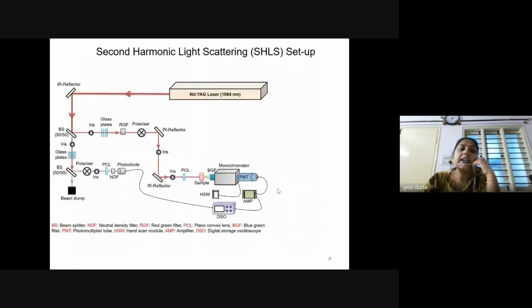Now, further, since most of the reports on carbonaceous nanoparticles were already done for their linear fluorescence and linear optical properties, we were quite interested in probing the nonlinear property of these carbonaceous nanoparticles, for which we opted for a second harmonic light scattering method. This is a SHLS setup which was made in our lab. Here we have used an Nd:YAG laser with 1064 nanometer wavelength radiation. We guided this radiation through a couple of optics to our sample, and the scattered light was collected using a monochromator, with a photomultiplier tube for the detection of the signal.